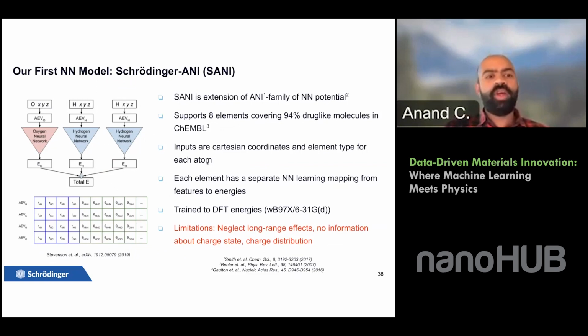So we came up with the first generation of model, the SANI model, which is the Schrödinger-Ani model, which is based on the Ani family of neural network potentials. And it initially supported a coverage of 8 different elements. And the architecture is very similar to many of the Behler-Parrinello architectures that many of you would have known. For example, you have a separate neural network for each element, and you calculate the energy contributions from each atom in your system, and you sum up the energy contributions to calculate the total energy of the system. And of course, this was trained to DFT level energies.